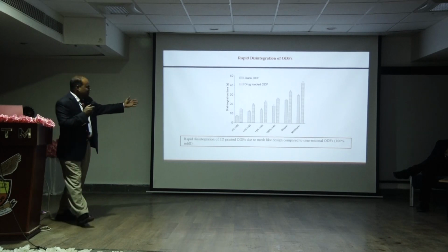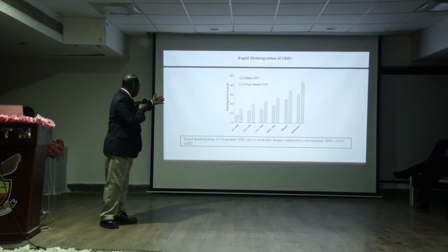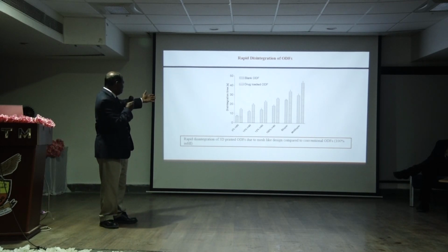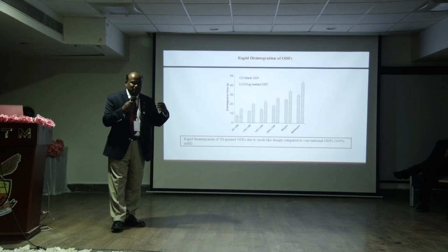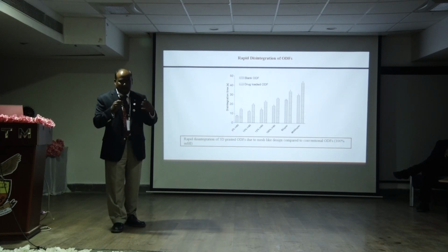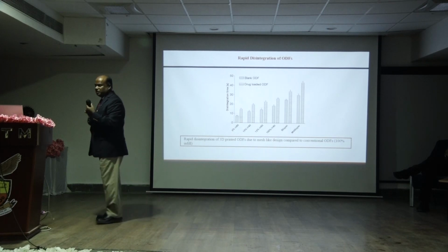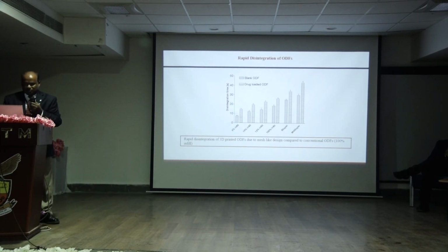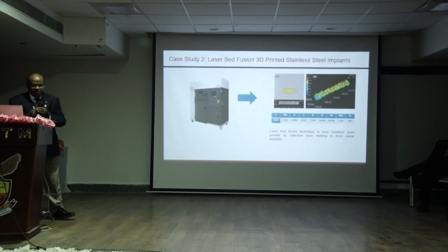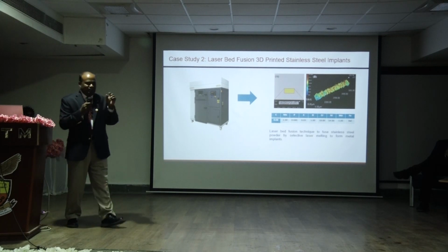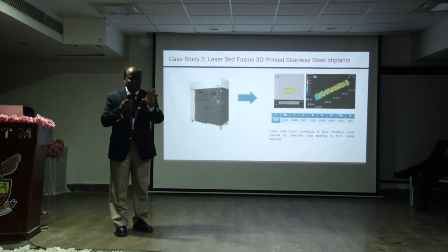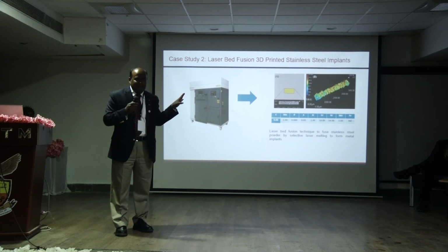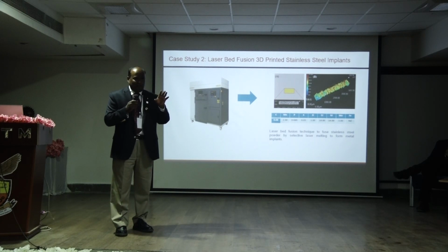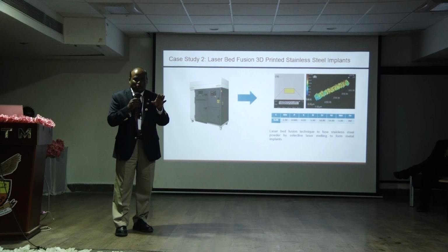And see the rapid disintegration here, we're pretty fast. Within, even with multi-layer films, they all disintegrate within less than a minute. So that is the benefit of orally disintegrating films, and which is facilitated by 3D printing process. And the second case study, where we made stainless steel implants. I'm not going to bore you with this example, but all we have done here is the doctors basically require